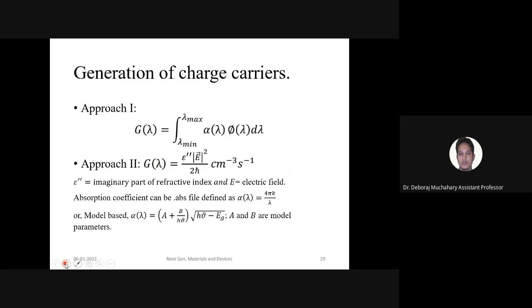Now we have the generation profile. I have been mentioning that the generation is a very important parameter. You can calculate generation in two ways. One, using FDTD you can find it using this equation. Here E is the electric field, so you will be needing the electric field. If you have the electric field, you can calculate the value using this type of formula. Otherwise, if you have the absorption coefficient alpha, using this formula you can calculate the generation also. And alpha is given by this type of modeling, that is the square root model, and A and B are some constant parameters that you have to define from the practical value.